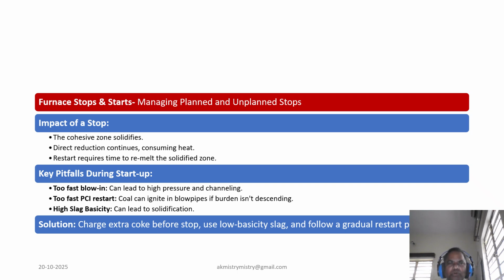Too fast blow-in causes channeling, too fast PCI restart risks blowpipe explosion, high slag basicity leads to solidification, and so many more. The solution is a master class in preparation. Charge extra coke before the stop, use fluid slags, and follow a meticulous gradual restart procedure. Patience is the key to speed here.